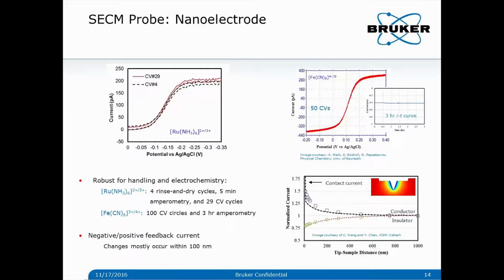It's actually the coating layer. So if your sample surface is too rough, for example more than 250 nanometer, it's going to be challenging because the tip cannot even touch the bottom. So that's one of the limitations. Stability, I just showed you several examples in the slide that Ravi showed here. We can do 100 CV cycles. We do 3 hours of amperometric measurement, and you can see that the tip is really stable. And we have customers that use the same tip for more than a week, daily. So the tip is actually quite robust.